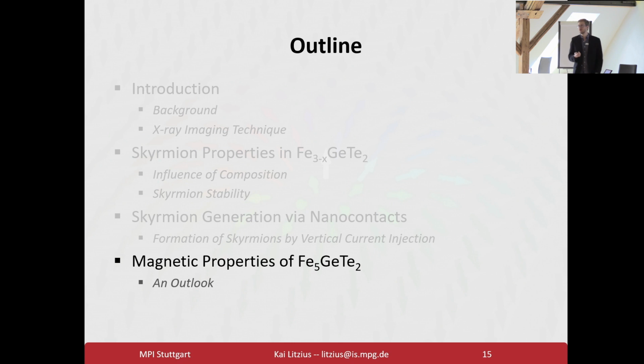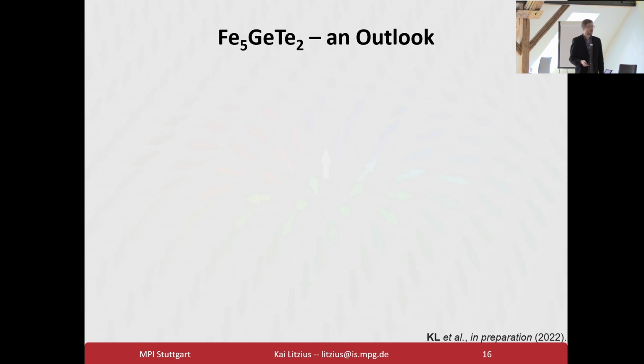This particular material is promising and has been studied in different forms, coming in annealed and in quenched states, meaning that once you grow it, you can either cool it down very quickly, this is the quenched one, or you heat it up for an extended period of time, allow the atoms to rearrange and to relax into different positions, and that's the annealed one. Usually the quenched one shows really interesting properties for, for example, SQUID and crystallography measurements, and we just wanted to look at the state in STXM to make sure that it's actually a good crystal, let's put it that way. You'll see in a moment why.